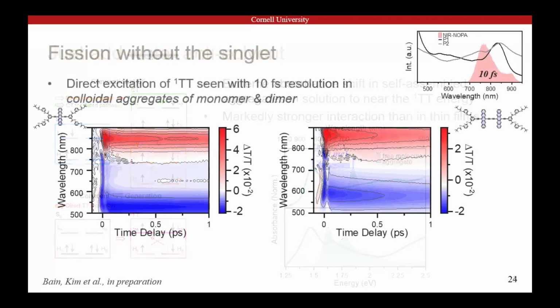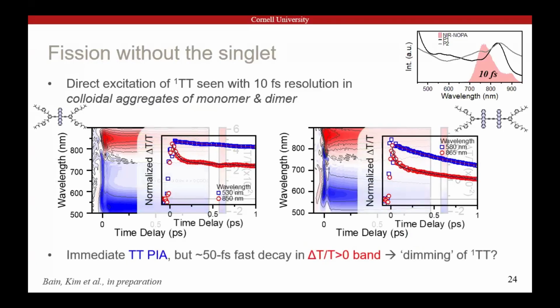And now, when we look at the transient absorption spectroscopy, we see what we've been looking for all along. No matter where we photoexcite in these aggregates, the only thing we see is this triplet pair state, down again to the couple of tens of femtoseconds that are defined by our instrument resolution. There's an initial decoherence or dimming of this state, which should be dark, but is clearly bright because it defines the UV-Vis absorption spectrum. But basically what we've been able to do by ramping up these charge transfer couplings is turn this nominally dark triplet pair state into the primary photoexcitation of the system. So one photon is now actually exciting two electrons, two excitonic states simultaneously.